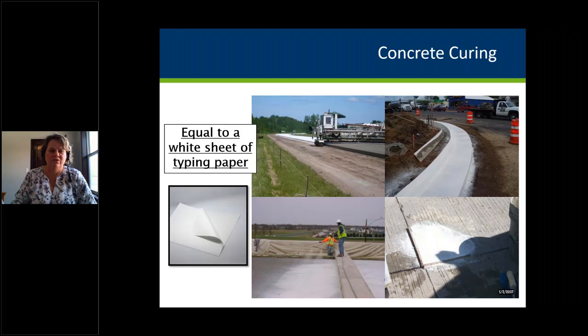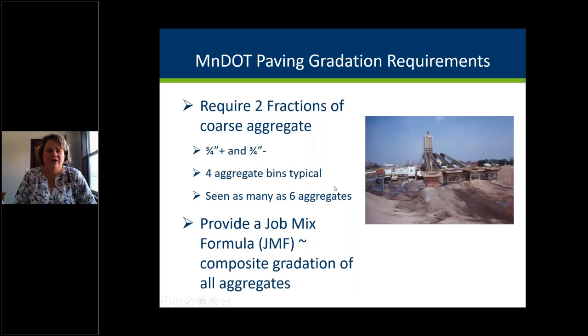It was funny that when we started pushing this, the contractor personnel on the cure carts would be looking at me all the time, pointing and saying, is this good enough? So very critical. Our aggregate requirements. With our new specifications, we've got water cement ratio and we've got aggregate requirements. So we actually require two fractions of coarse aggregate, a 3/4 plus aggregate and a 3/4 minus aggregate. What we wanted to do was really encourage the contractor to get more aggregates into their mix, because that was really all they were using.